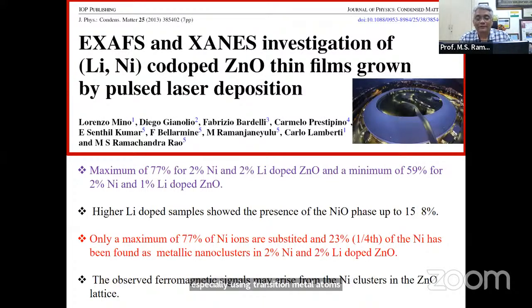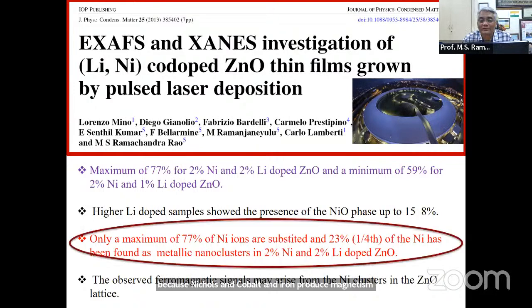For many years, people have tried to look at magnetism, especially using transition metal atoms like nickel, cobalt, and iron. We have busted this myth saying that don't talk about magnetism when you're doping transition metal ions, which are already magnetic. The magnetism is not because they get doped and inherently produce magnetism in those lattices. It's just because nickel, cobalt, and iron produce magnetism in the form of clusters in the solid.